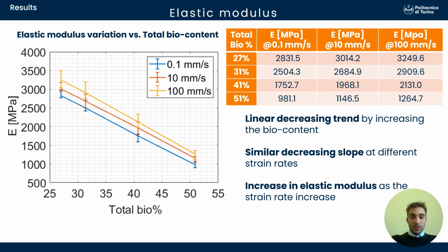In this slide, I reported the values coming from the tensile test for the elastic modulus, considering the 4 different tested materials and 3 different strain rates. As you can see, by increasing the bio content, we have a linear decreasing trend, and this decreasing slope is almost the same for the 3 different strain rates. By increasing the strain rate, we have an increase in the elastic modulus.